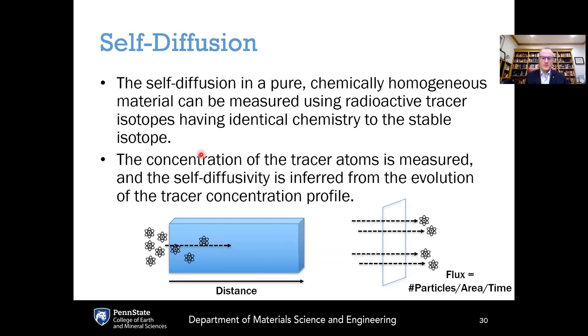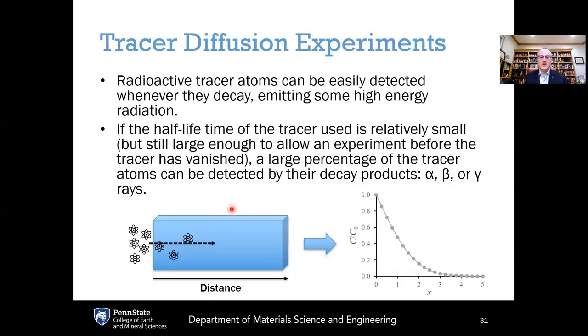So with self-diffusion, what you do is put a layer of the radioactive isotope on the surface of the sample under study, and then expose it to a heat treatment at a certain temperature for a certain time, allow diffusion of the radioactive isotope into the material, and then measure how much of that radioactive isotope you have as a function of depth into the material. So radioactive tracer atoms can be easily detected whenever they decay, emitting high energy radiation.